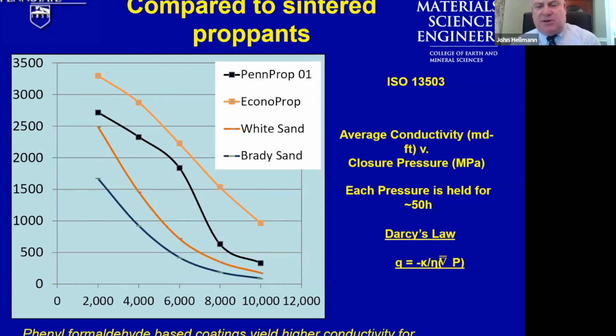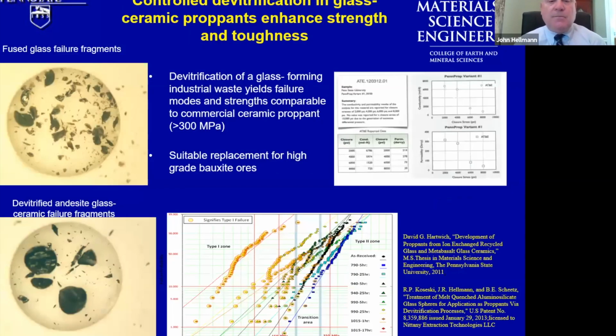We compared these materials using the ISO 13503-2 or API 61 permeability test. We found that these materials, which we're now calling PennProp, which was a trademark name developed by the Nittany Extraction Technology Company, performed very, very admirably well compared to state-of-the-art proppants that were readily available at low cost in the industry, and that these materials were performing this way without coatings. The PennProp materials did not need coatings to perform as well as the industrial materials that were available. So this devitrification processing allowed us to form a glass ceramic material that failed in type 1 mode, possessed high enough strength and great permeability relative to commercially available materials.